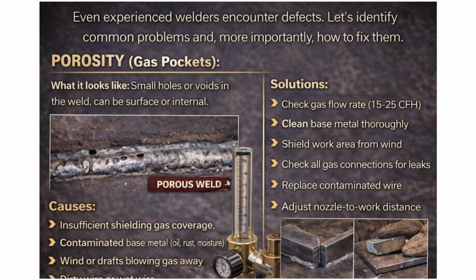Let's identify common problems and, more importantly, how to fix them. Porosity, gas pockets. What it looks like: small holes or voids in the weld, can be surface or internal. Causes: insufficient shielding gas coverage, contaminated base metal, oil, rust, moisture, wind or drafts blowing gas away, dirty wire or wet wire, gas leak in system, travel speed too fast.